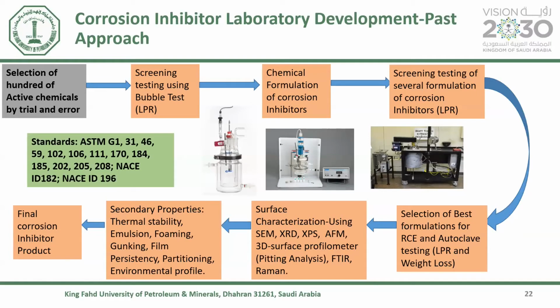So here I want to describe corrosion inhibitor laboratory development, the conventional approach. The normal selection is done by, first of all, selection of hundreds of active chemicals, normally done by trial and error. So many libraries of active chemistry are screened, and then they are tested using the so-called bubble test, just to screen them. And then after screening, a few of them that are performing will be moved to the next stage of chemical formulation, and then they will further undergo some screening tests to select the best formulation.